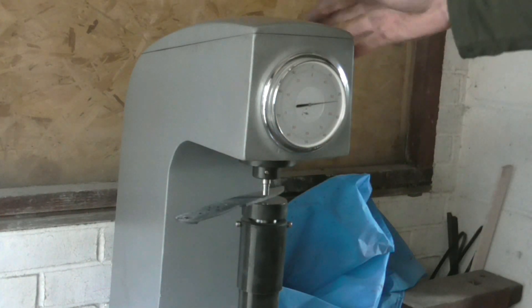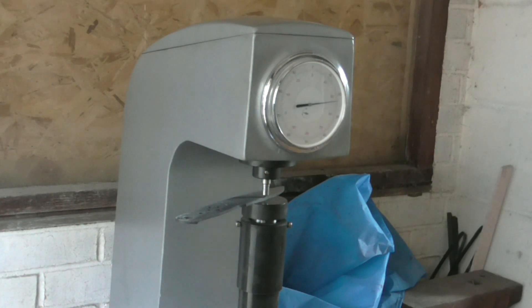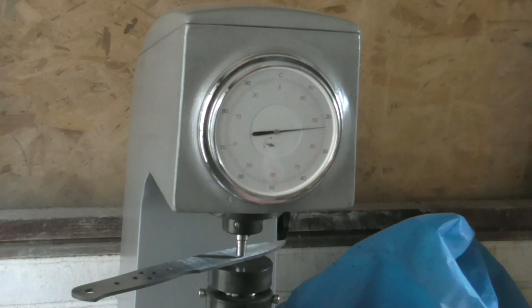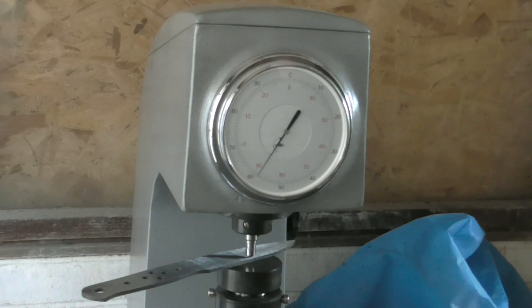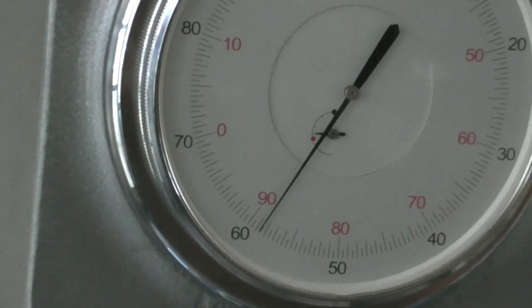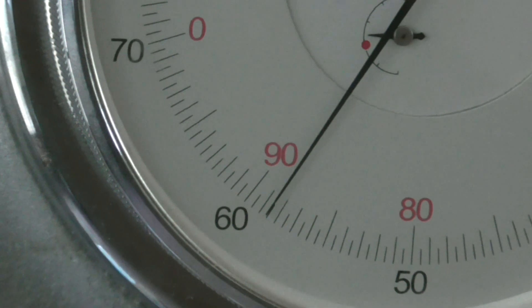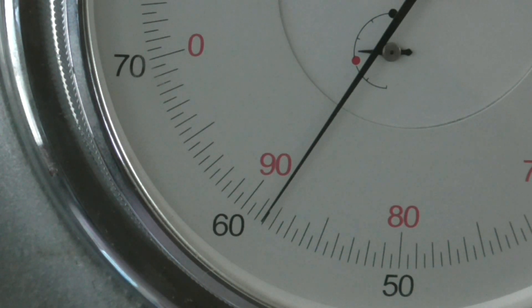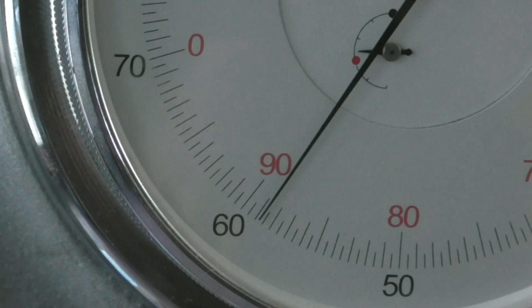Let's have a look at that then — I'll bring you in for the critical moment. I'm just going to unload it and you'll see where it's at. There we are — that's looking good. Reading 58.7, 58.6, 58.7 — I'm almost 59, so I'm happy with that.